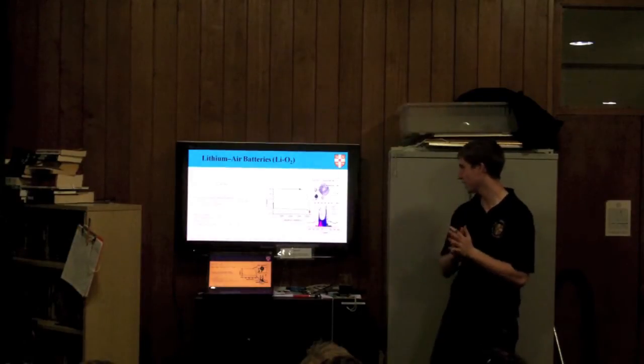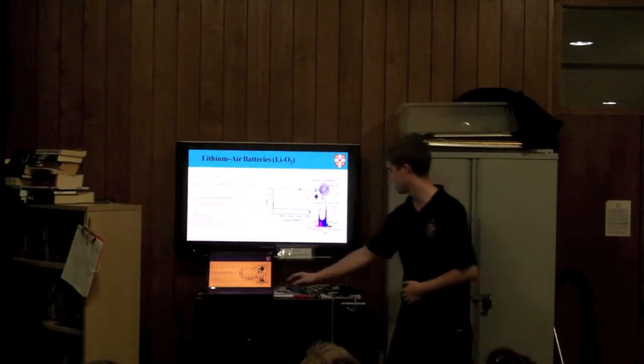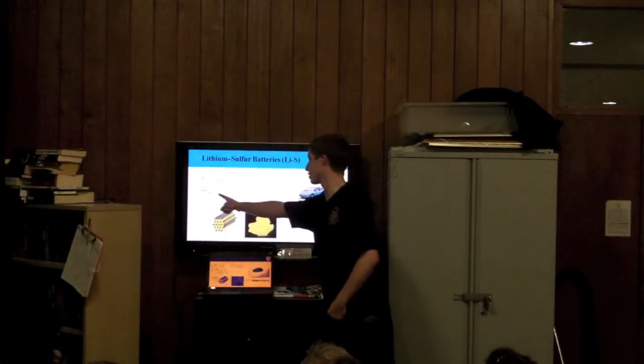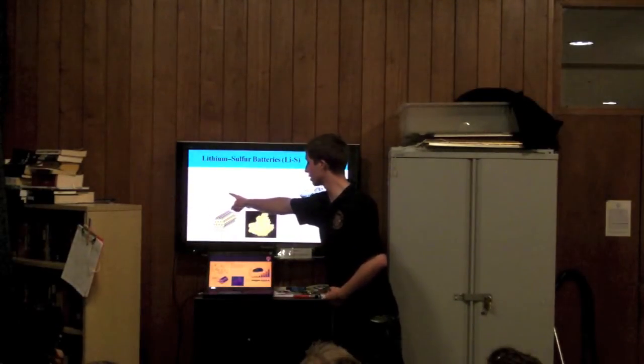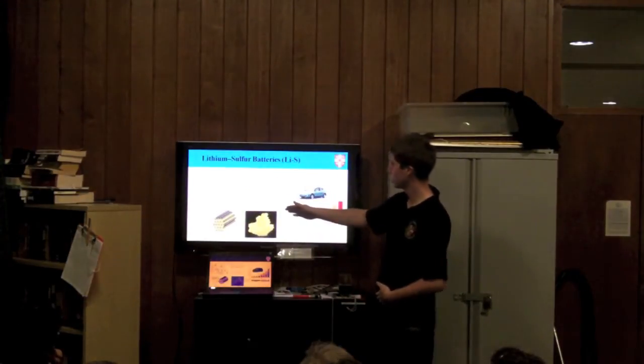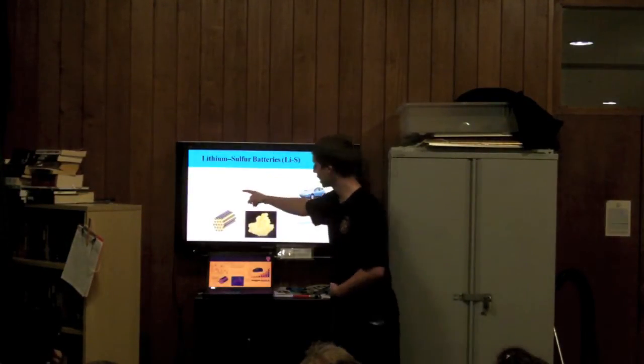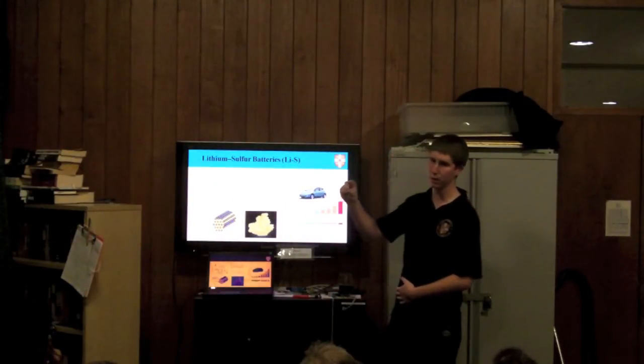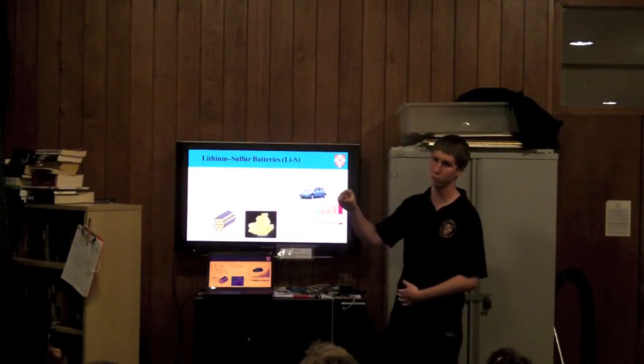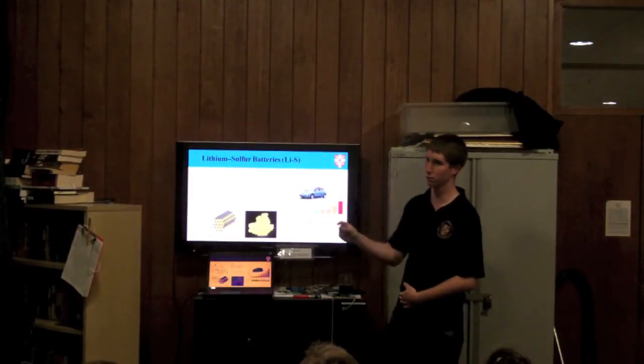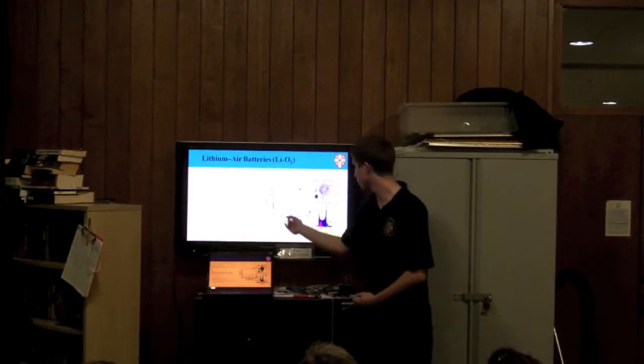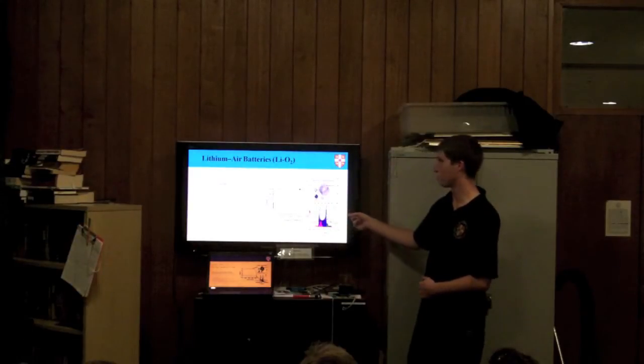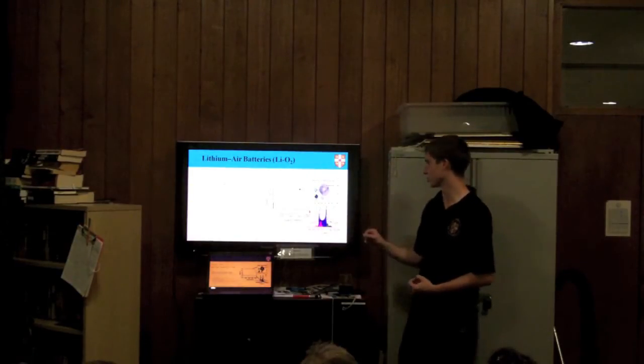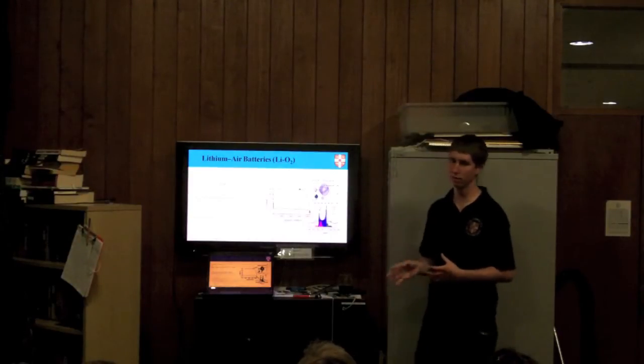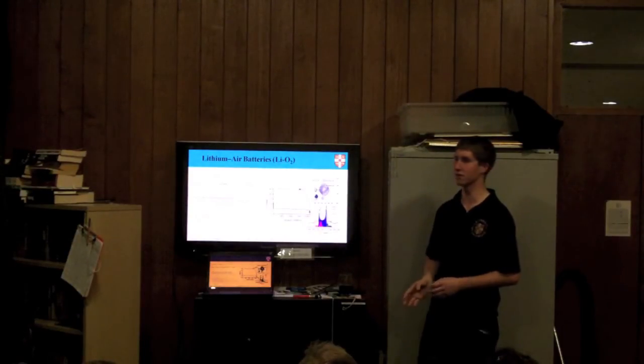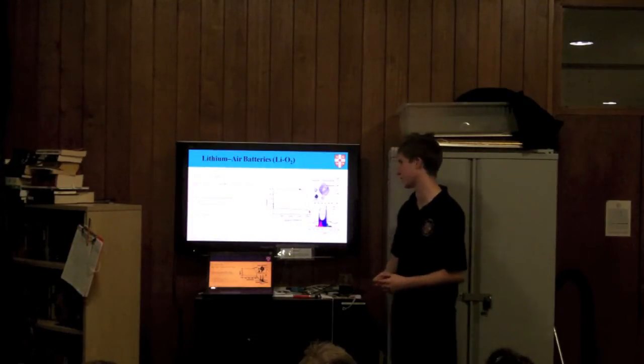And so one of the things on maybe this other plot I showed you, I didn't explain this really yet, but this bottom plot, the bottom part of the curve is as you discharge, how much potential you get back, and then as you come back up to the top, it's recharging. So if there's a gap there, that's kind of the overpotential. That's how much extra energy you have to put in, which is basically a loss. That's bad for energy efficiency. This is what the one for oxygen looks like. It's way worse. It's basically double. So you're basically losing half the energy every time that you put in anyways. That's not even close to the only problem, but it's only basically half efficient right now.